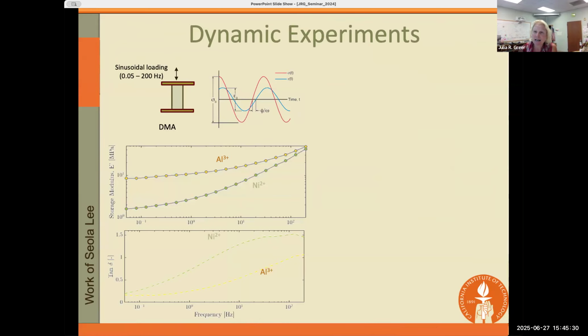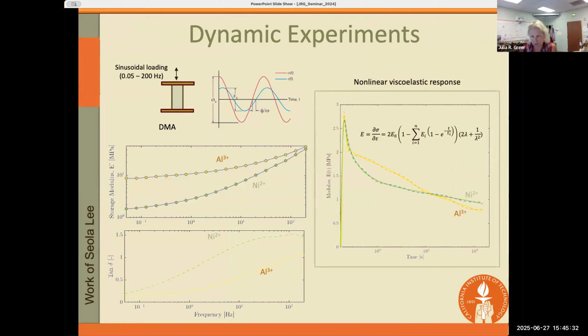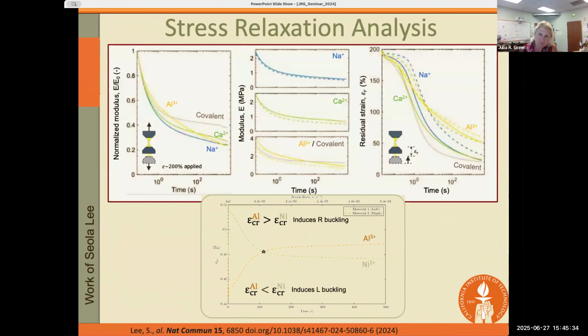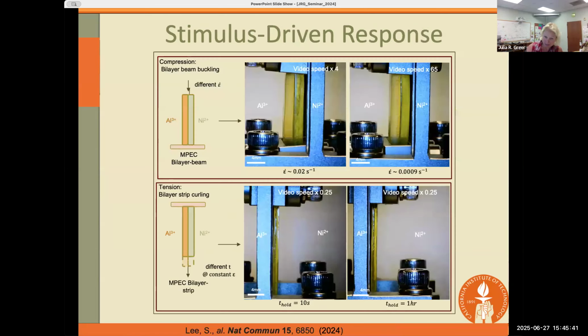And then the last thing I'd like to share with you is that with some mechanical modeling, and recognizing that these hydrogels infused with different metal ions have different time constants, we can really control their reconfigurability. So what I'm going to show you here is the deformation of a bilayer strip. The aluminum is on the left and the nickel is on the right. Again, it's the same polyacrylic acid based resin, and now it's infused with aluminum on the left and nickel on the right.